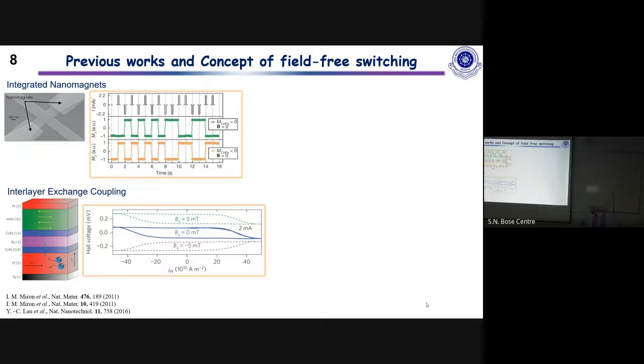And another way people did was they used interlayer exchange coupled magnets. So in this case, they had this cobalt iron layer which has a perpendicular magnetization, and they exchange coupled it to another cobalt iron layer through a ruthenium spacer. And this interlayer exchange coupling was a source of magnetic field that broke the rotational symmetry. However, this is very challenging from the fabrication point of view, and also because you need to have the right thickness or adjust thickness so that you can get a considerable magnetic field to break the rotational symmetry.